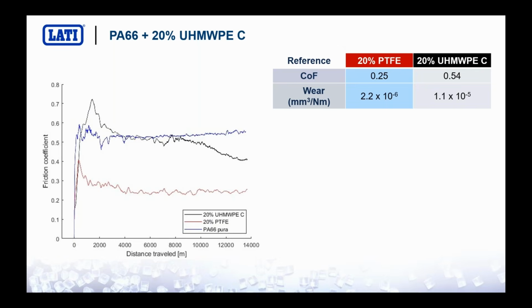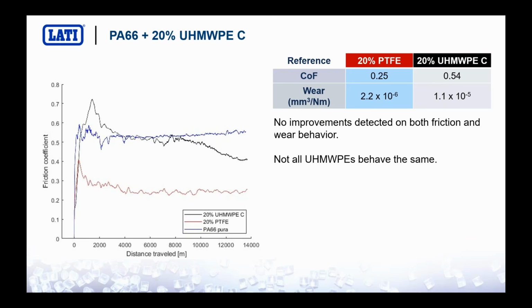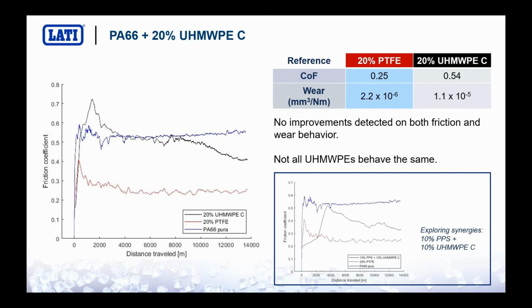Then we started to analyze the well-known additive used in the market, the ultra-high molecular weight polyethylene, C. C stands for the entry level, so the cheaper version. And as you can see, we didn't obtain, in this case, any positive results. No improvement from both friction and wear resistance. But fortunately, not all the ultra-high molecular weight polyethylene behave in the same way, like we will see in the next few slides. But this slide is important also to remind you of the synergic effect that we have already discussed.